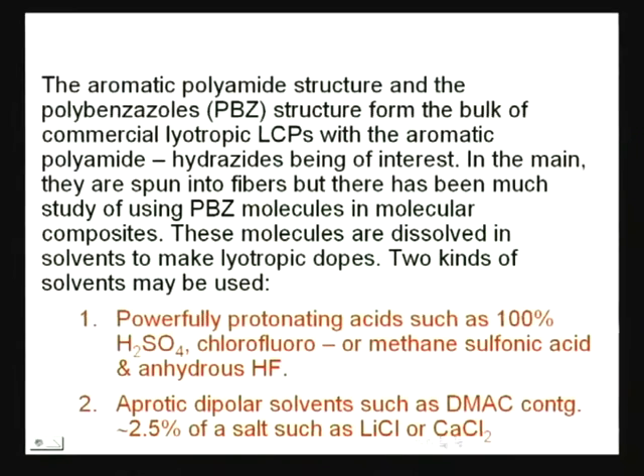Aprotic dipolar solvents such as dimethyl acetamide containing 2.5% of a salt to increase the polarity. Actually, these materials, lithium chloride or calcium chloride, they increase the polarity of a solvent. Sometimes if a solvent is unable to dissolve a solute, then you add certain electrolytes there which will increase the polarity of the solvent, and that will easily dissolve the solute.